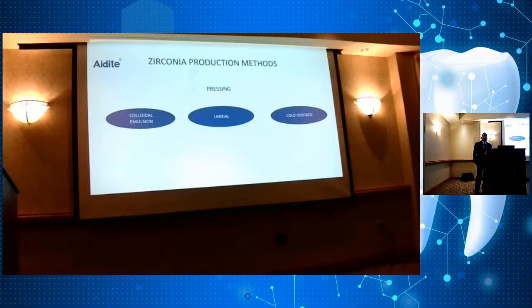So you should be asking your manufacturer or supplier, what type of pressing are you using to manufacture these discs? And if it's not cold isostatic pressing, chances are that you may get some issues with the disc. If it's cold isostatic pressing or CIP, you are assured that this disc has the correct density of 65 MPa, and that's what we recommend, so that your tools are working. You can produce maybe 200 to 300 millings at a time before you need to change your tools. Okay, so at 65 MPa, we're finding out that your material will work really well in your milling machines.